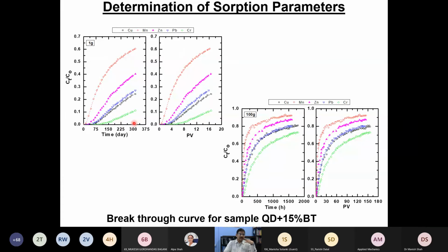At 1G, even after 300 days, for example in the case of chromium, the Ct by C naught seldom reached very close to 0.1. In order to get any meaningful parameter from this kind of breakthrough curve, you need to project the value of Ct by C naught, at least it should be able to reach 0.5. Can you imagine how much time it will take to reach 0.5? Maybe at least 4 to 5 years, it cannot be less than that.